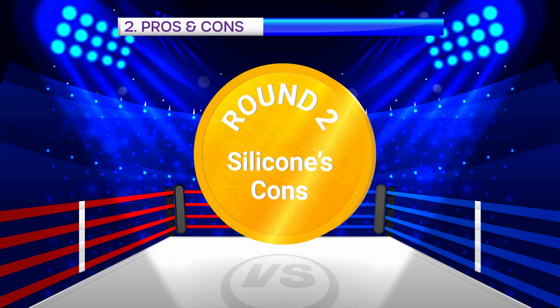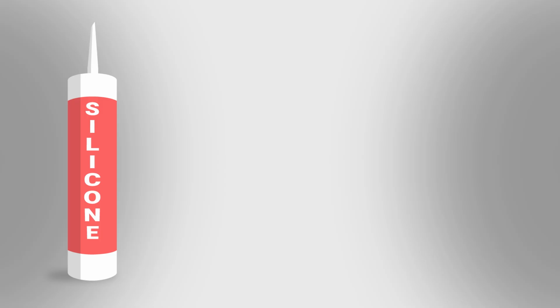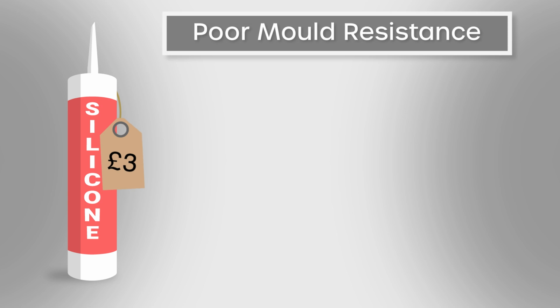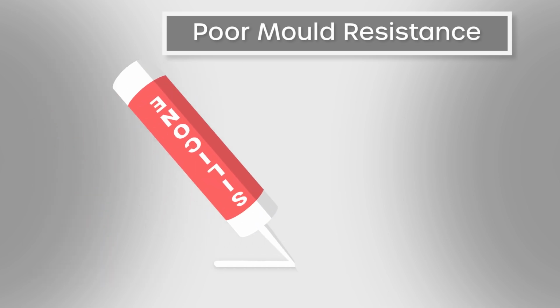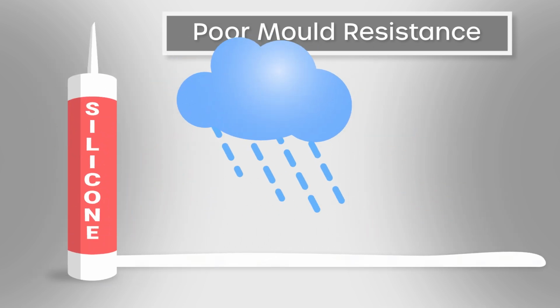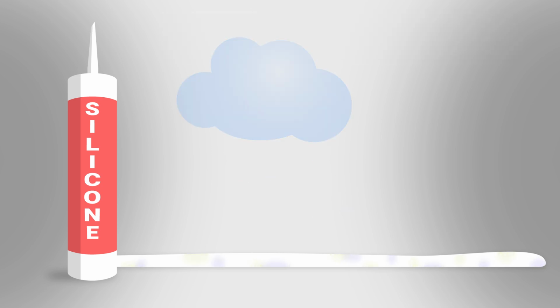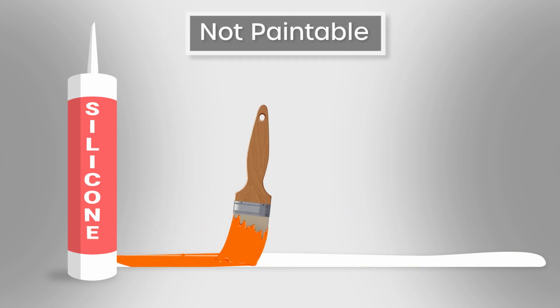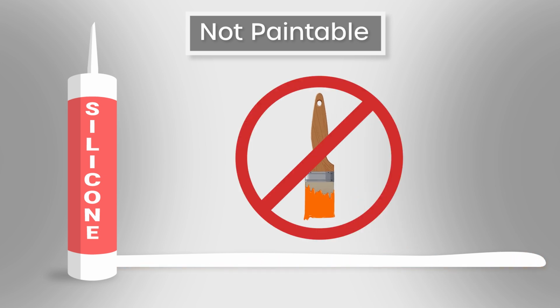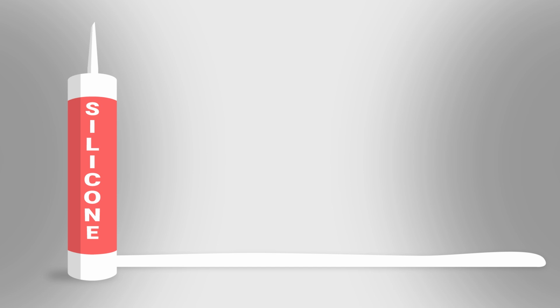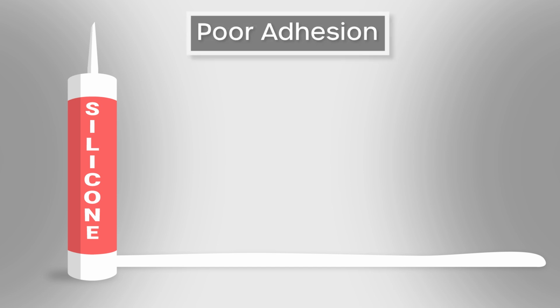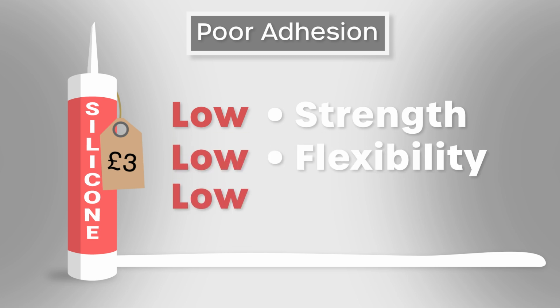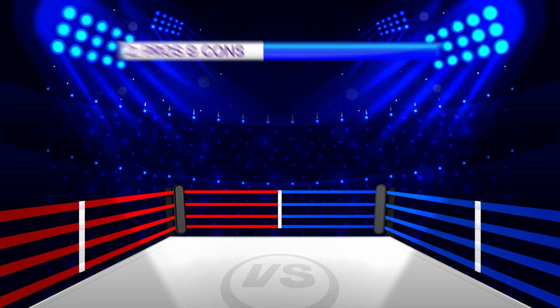Silicones have several disadvantages as well. A cheap silicone that would cost around £3 a tube would have poor mold resistance. If you intend to use this in a very humid environment, you'll start to see your silicone go moldy after 6 months. Another disadvantage of silicones is that you cannot paint over them. This is due to the hydrophobic nature. But most importantly, the biggest disadvantage of silicones is their poor adhesion performance. The silicone sealants that are readily available at low cost will not have enough strength, flexibility or grab to be used for bonding purposes. We will demonstrate that in a minute with our live comparison.